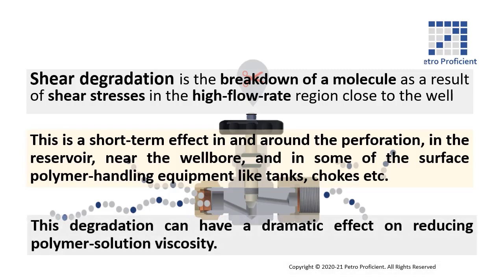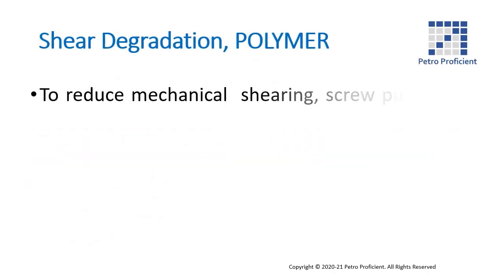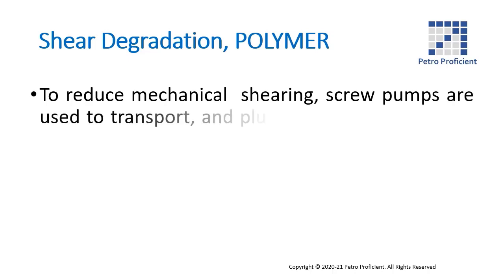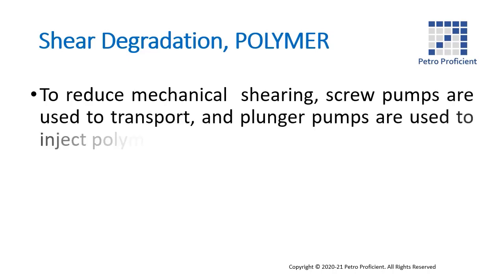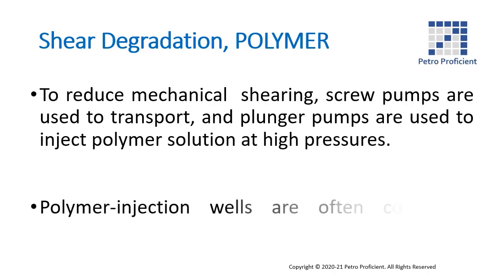This degradation can have a dramatic effect on reducing polymer solution viscosity. To reduce mechanical shearing, screw pumps are used to transport, and plunger pumps are used to inject polymer solution at high pressures. Polymer injection wells are often completed through perforations.